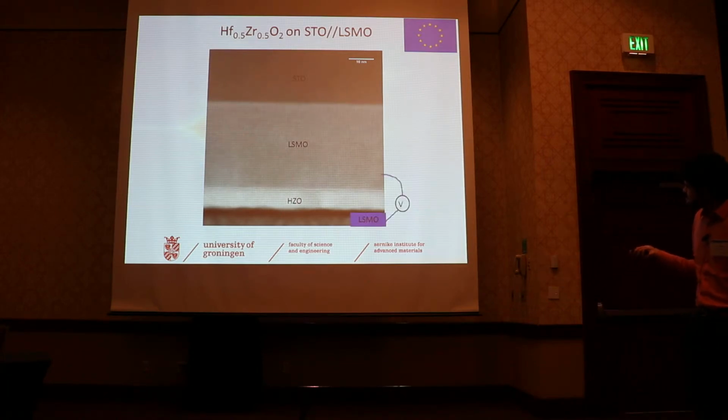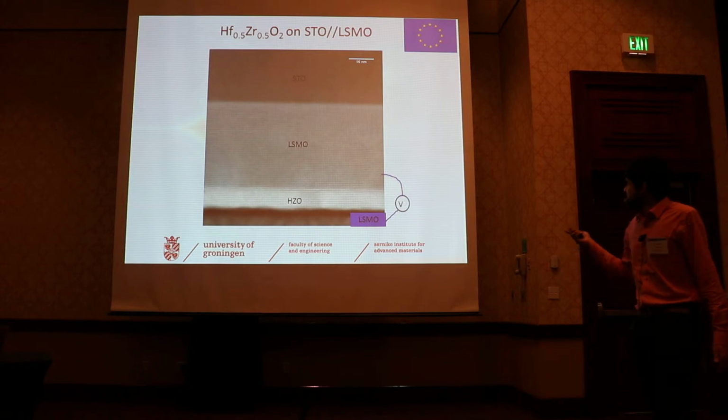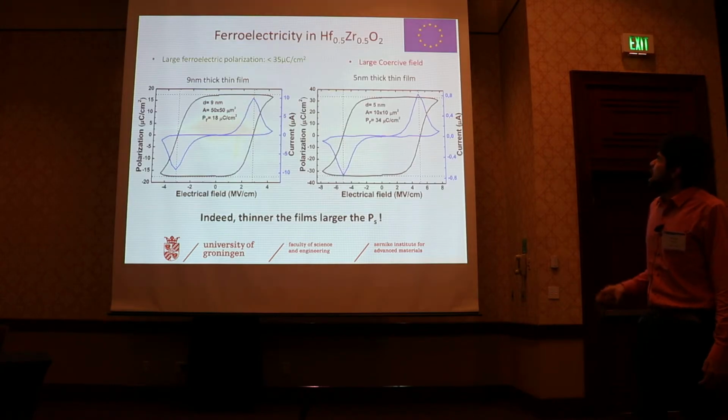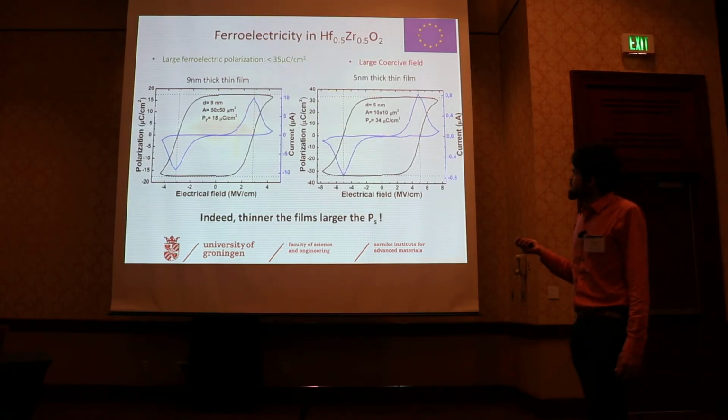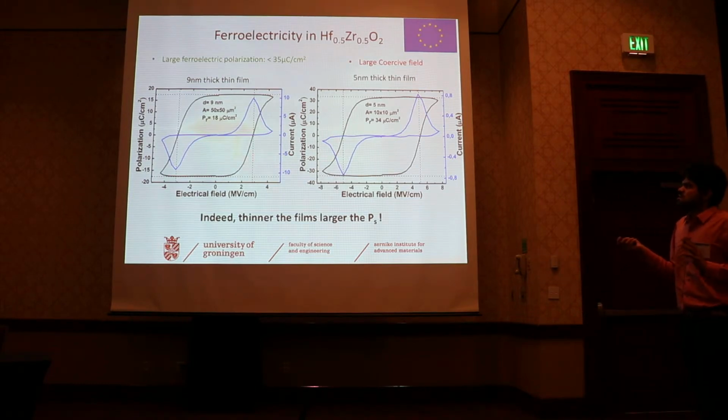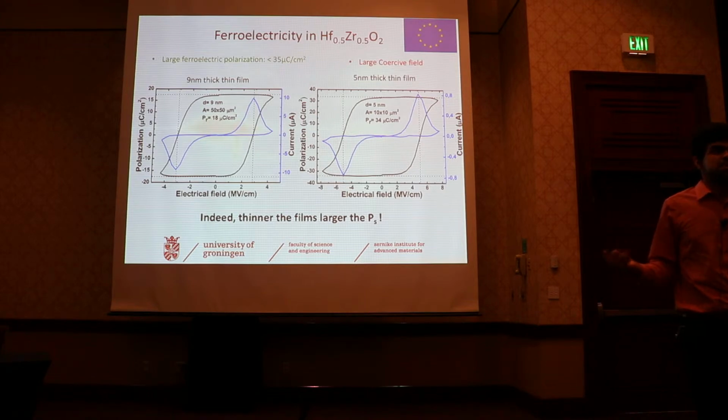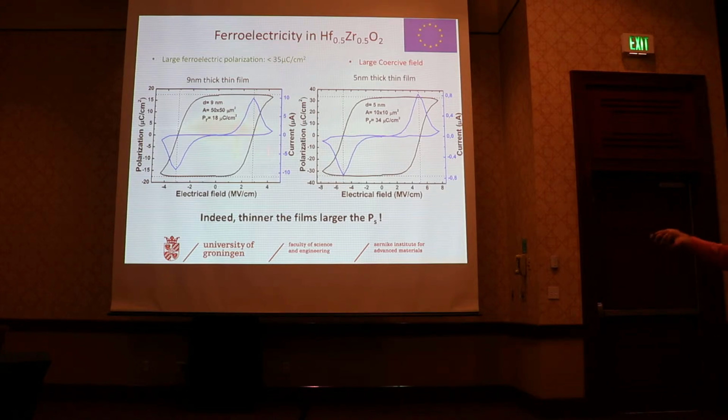And we characterize this by lithographically patterning another top electrode, and voila, we see ferroelectricity. And these films are ferroelectric even in the first cycle. They don't sleep. They don't need to be woken up.